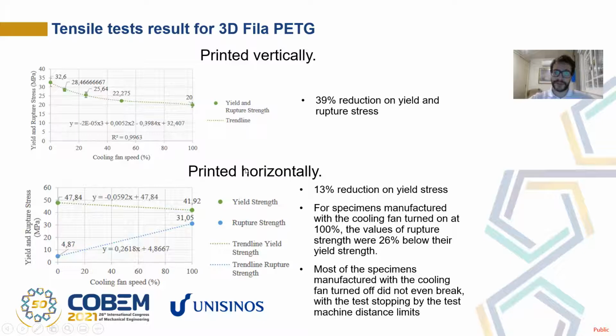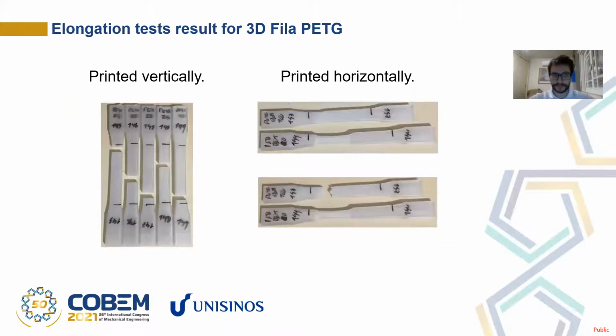And for the ones printed horizontally, the yield stress reduction was about a 13% drop between the cooling fan off and on at maximum. And for the rupture strength, here the behaviors really change. You can see that this one is quite below because most of the test specimens did not even rupture here. And here they rupture after forming the neck.